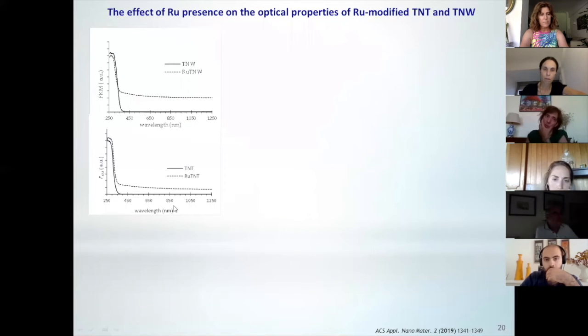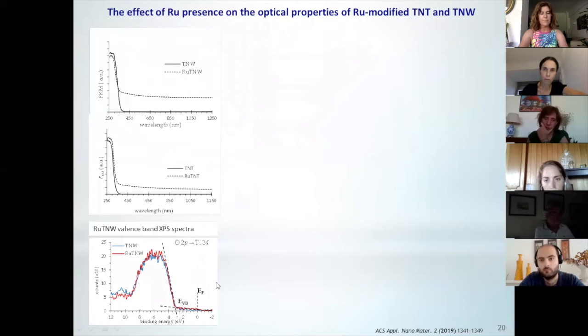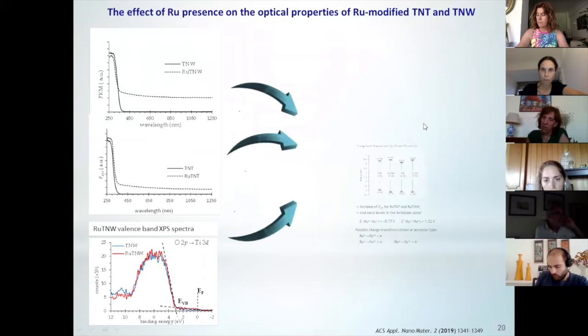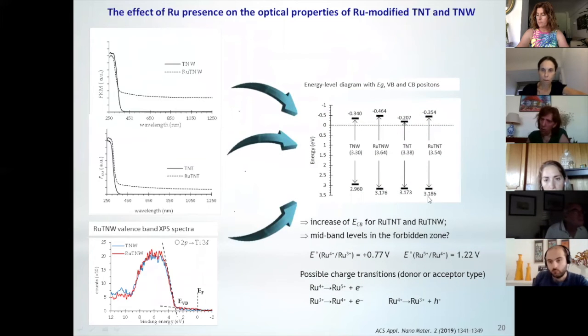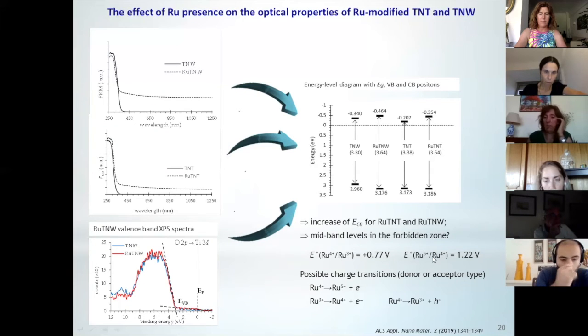Then we decided to study the optical behavior of these samples. As you can see here, we have a slight shift in the absorption edge of these materials. And when we combine these results with the ones obtained by the XPS valence band spectra, we can see that we know exactly where is the position of our valence band, conduction band, and of course band gap. Okay, and this is very useful because it tells us that in fact our metal ruthenium can be here in the forbidden zone and can act as a scavenger, donor or acceptor type, depending on the position of the energy level.